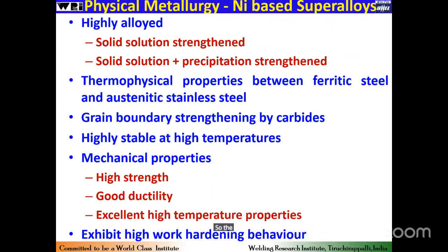So the physical metallurgy of the nickel-based superalloys, it is highly alloyed. So it has two kinds of strengthening. One is solid solution strengthening, and the other one is solid solution plus precipitation strengthening. When we talk about the thermophysical properties, especially the coefficient of thermal expansion, thermal conductivity, and so on, it is going to be between the ferritic steel and austenitic stainless steel. And grain boundary strengthening by carbides, but this is not very new. It has been happening in our chromoly steels as well. Highly stable at higher temperatures. So that is the thing that is being brought by these advanced grades of materials.